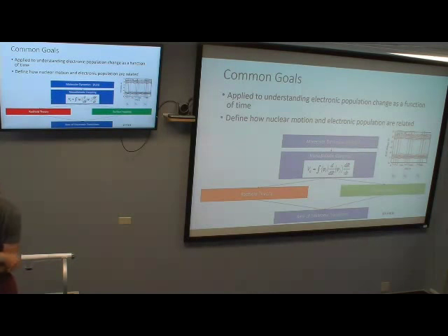From a theoretical point of view, a lot of our work has always been rigid semiconductor materials, whether nanoscale or two-dimensional bulk. When you have rigidity in your structure and you don't have a ton of nuclear fluctuation, going through Redfield can save you quite a bit of time because your bands aren't going to be crossing or bending as much.